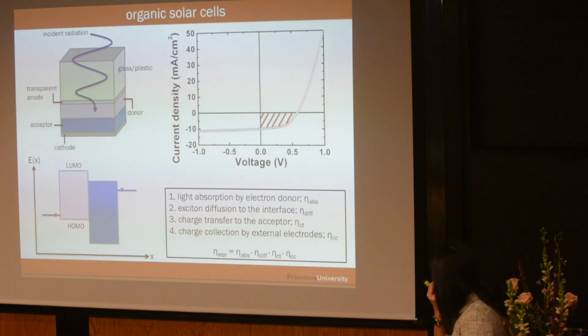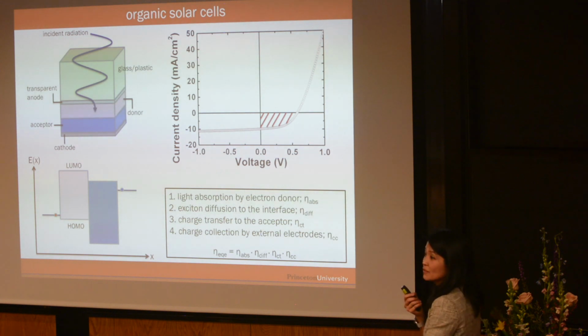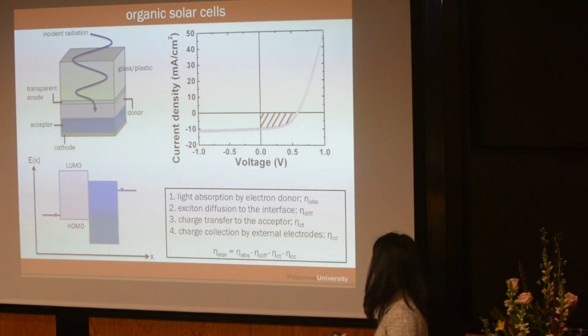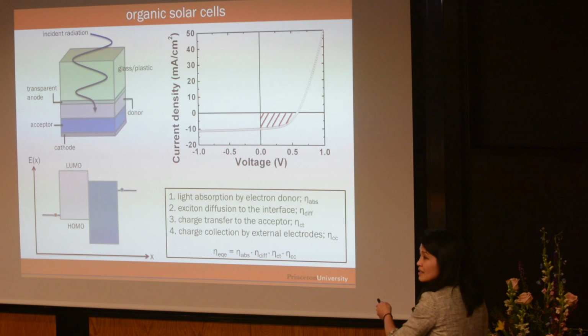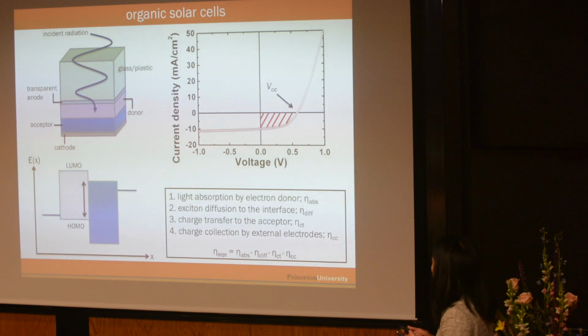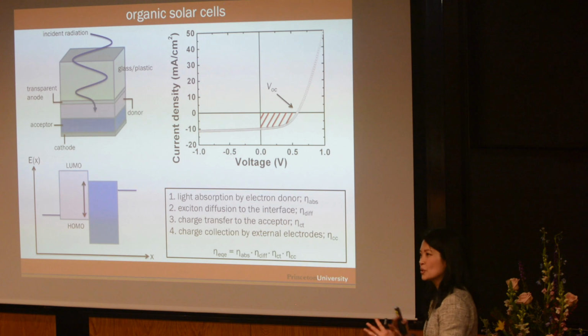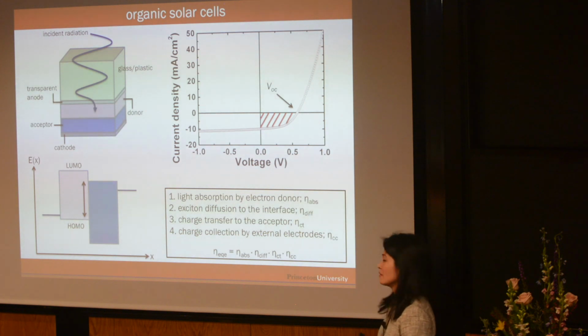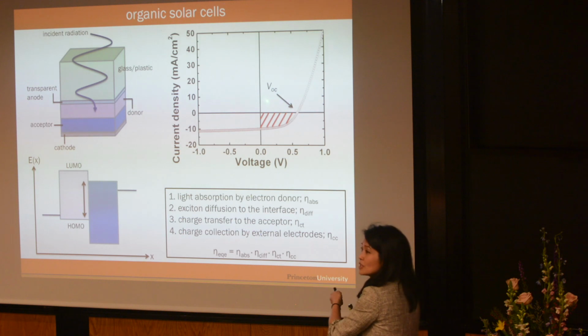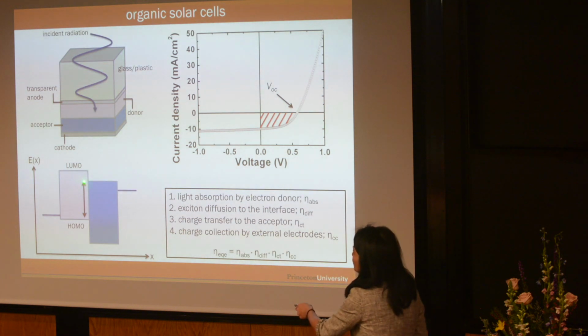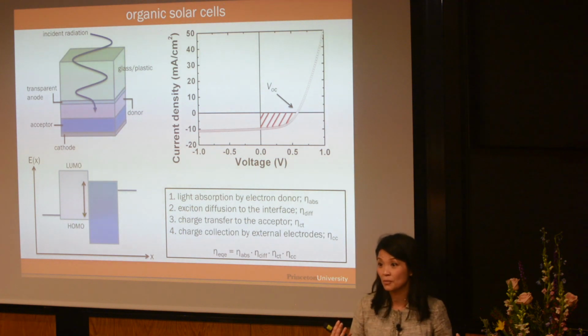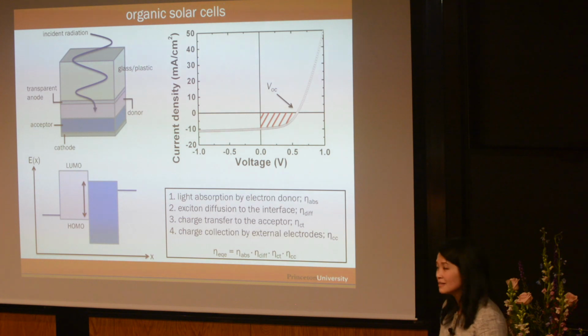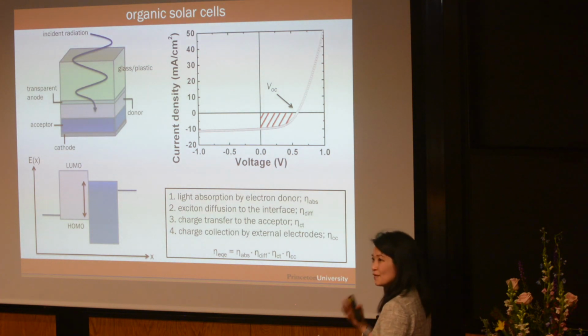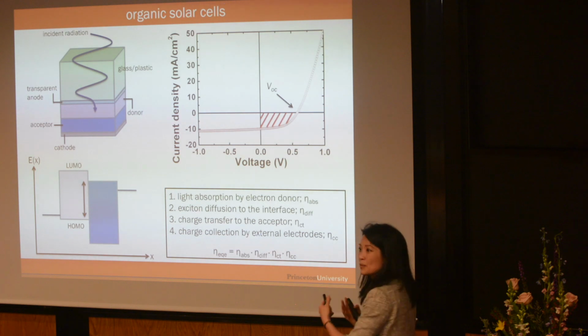The way one quantifies solar cell operation is to look at current density as a function of voltage. So you have this square curve. The squarer the curve is, the better your solar cell is performing. And this area is the power generation area. You've got an open circuit voltage. And again, to first order, we know how to tune this by the selection of the materials pair. That open circuit voltage is dictated to first order by the difference between the HOMO of the donor and the LUMO of the acceptor. And again, these are materials properties, so you can go to a library and pick the materials. And to first order, if your materials behave nicely, you should be able to predict what the open circuit voltage is.